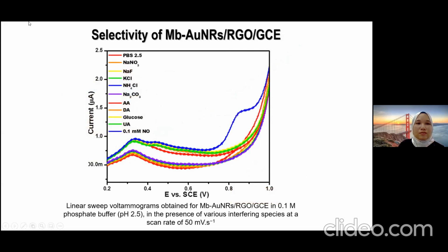So for the selectivity, we can also study it by using linear sweep voltammetry, in the presence of various interferences and also electrolyte ions such as KCl, NaF. As you can see from this LSV, there is only a peak appearing for the detection of nitric oxide. Other than that, we cannot see the appearance of any peak.